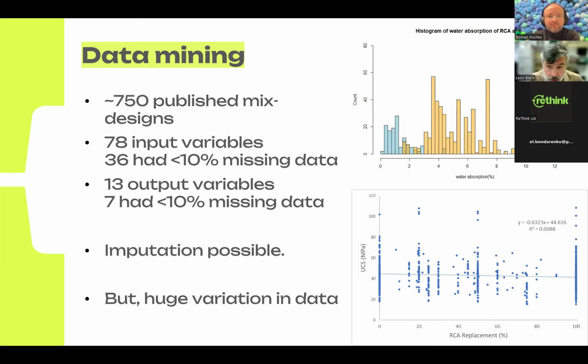So what we started to do, and we're doing this as part of one project and in S3 as well, is look at data mining. There is lots of work going on around the world on recycled aggregates. We found 750 published mix designs. These had all been through peer review, so in theory they were validated. And we found 78 input variables. Everybody reports how much sand, how much water, how much aggregate, how much cement. Some people report the size of the aggregate, some people don't. Some people report the water absorption capacity of the natural aggregate that was used, some people don't. So we identified 78 different variables.